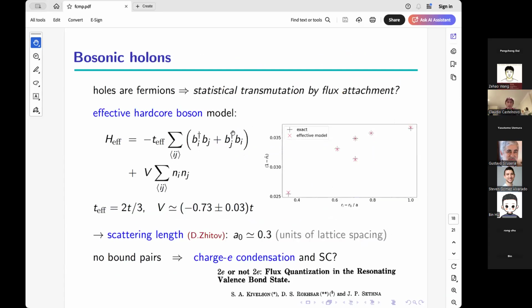This is the bosonic model I was mentioning. If the holes are bosons, we can assume that they are just hardcore bosons with tight binding on the pyrochlore lattice. And we add for fine-tuning some nearest neighbor repulsion that is our only tunable parameter. The hopping is effectively 2t/3 because there are only 4 out of 6 directions where the holes can hop in the original lattice, whereas these bosons can hop in all 6. So we need to rescale the hopping term.